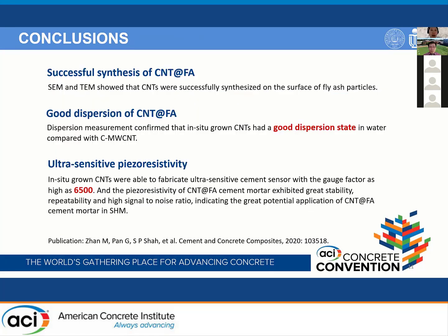According to the above experimental results, we can draw the following conclusions. Firstly, SEM and TEM showed that carbon nanotubes were successfully synthesized on the surface of fly ash particles, and the dispersion measurement confirmed that the in-situ carbon nanotubes had a good dispersion state in water compared with commercial carbon nanotubes. And lastly, piezoresistivity measurement showed that in-situ growing carbon nanotubes were able to fabricate an ultra-sensitive cement sensor with a gauge factor as high as